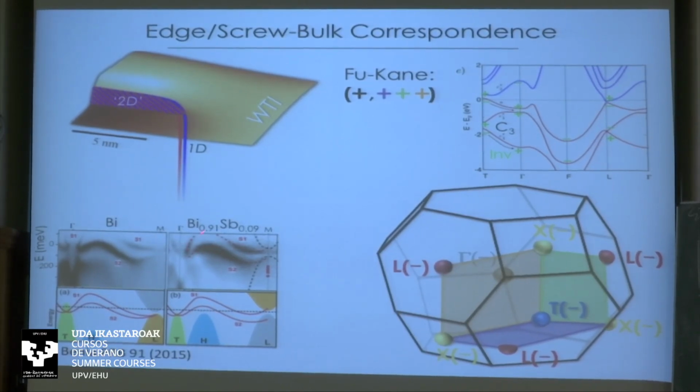So this clearly has two helical surface bands, and mainly this upper one, called S1, I think, starts from the valence band and terminates at the conduction band, which is not really apparent here around the endpoint. And this seems to be a valid helical surface band.